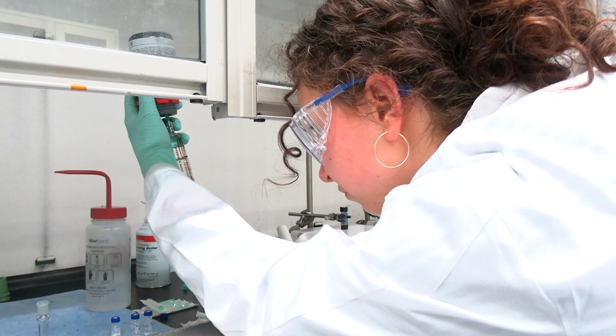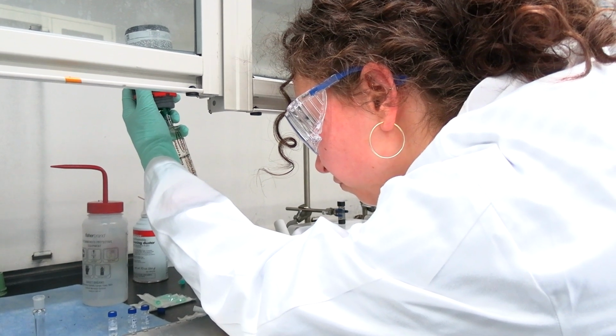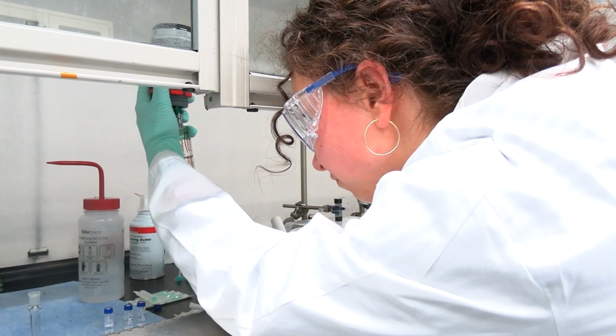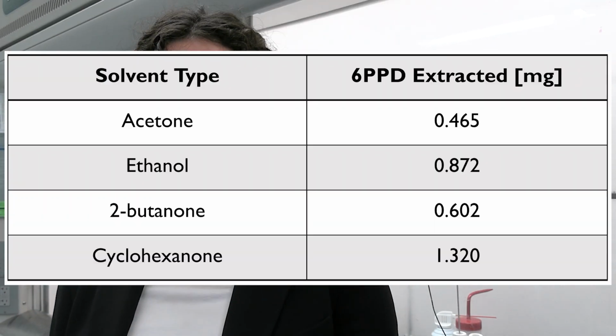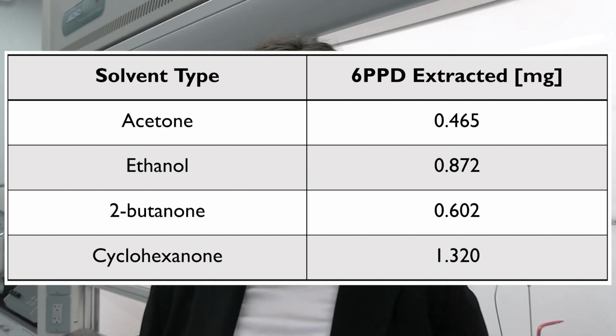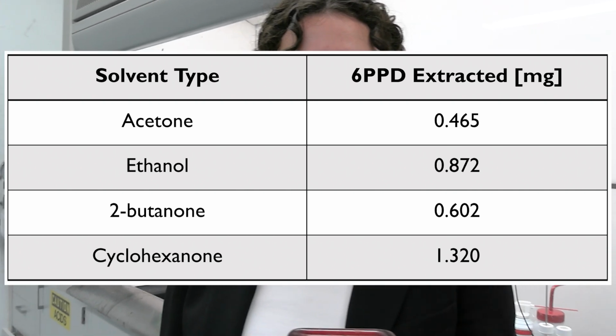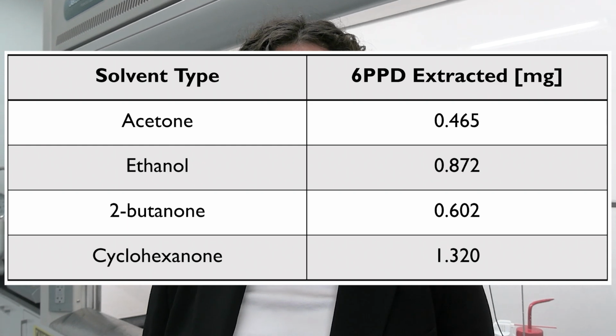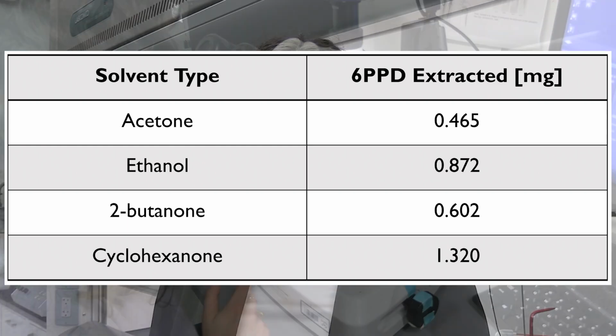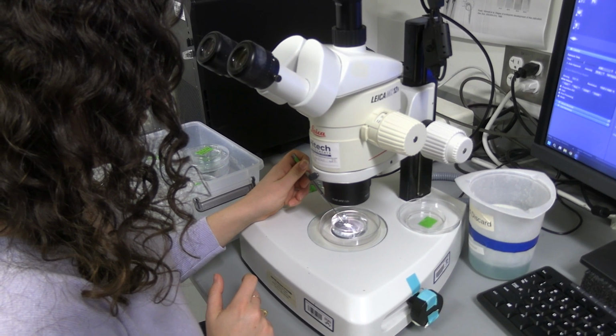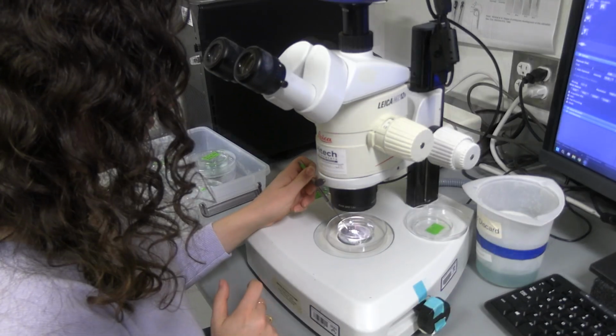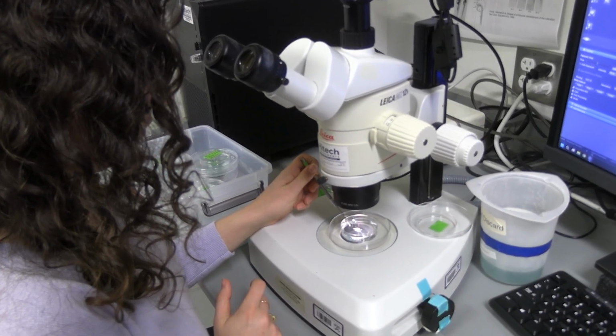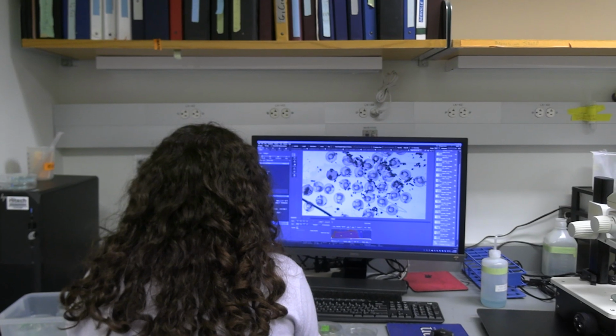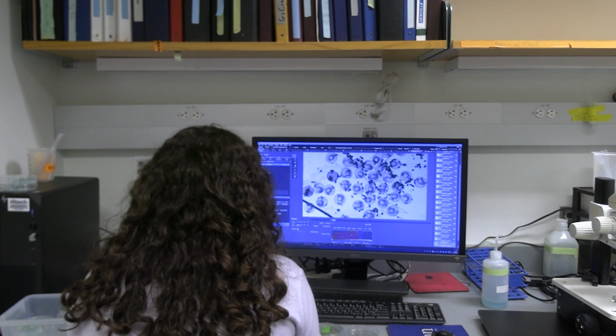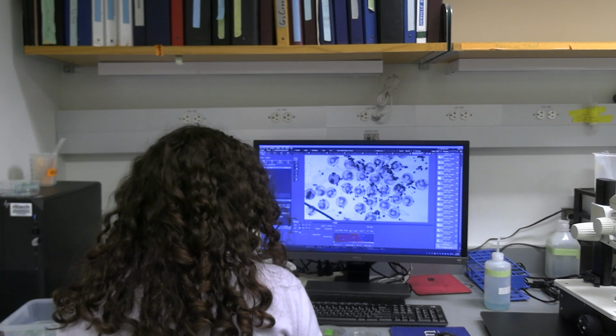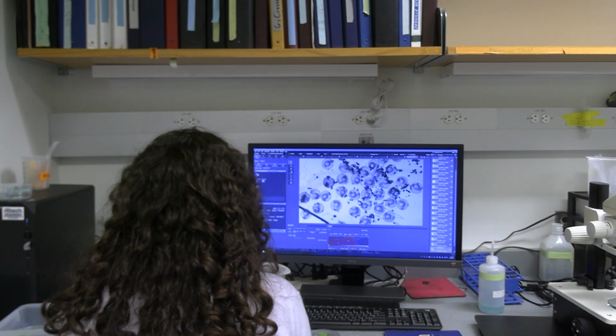Using our treatment method, we've been able to extract more 6-PPD than when the crumb rubber is left in water. Our most successful treatment method was using cyclohexanone solvent, where we were able to extract over 5% of the 6-PPD in the tire. This may not seem like much, but when the treated and untreated samples were put in solution and exposed to zebrafish, the treated sample resulted in no mortality of the fish. Recycling shouldn't come at the cost of public health or ecosystems.